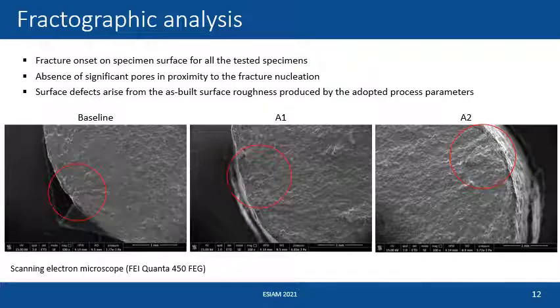For all the tested specimens, the fracture surface was analyzed by using a stereo microscope and a scanning electron microscope in order to understand where the fatigue crack onset is located and if near to it there are some pores or defects that can have affected significantly the fracture nucleation in this fatigue life. For all the tested specimens, the fatigue crack onset resulted to be located in proximity to the specimen surface. And as you can see from the three pictures taken by scanning electron microscope, represented here in the bottom of the slide, with the fatigue crack onset highlighted by the red circle, in proximity to it there are no significant pores or defects that can have affected the fatigue life.